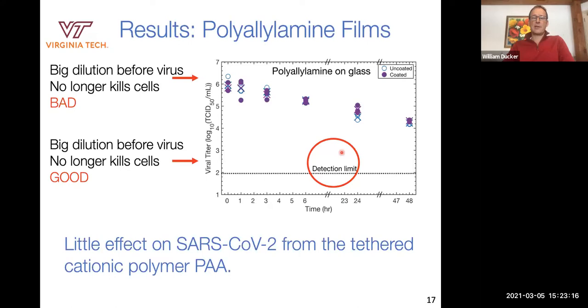So here are the results of our film. Here's the viral titer as a function of time. So 6 means you need a 10 to the 6-fold dilution, well, in fact, a 10 to the 4-fold dilution before you don't notice any effect. That's very bad. You have to dilute it a lot in order for it not to kill mammalian cells. And what we found with polyallylamine compared to glass, with a control uncoated and coated, was absolutely no effect. This is just the natural decline of the virus, which decays on its own. So there was no effect. This was very sad for us. My shot that I conceived didn't work at all.